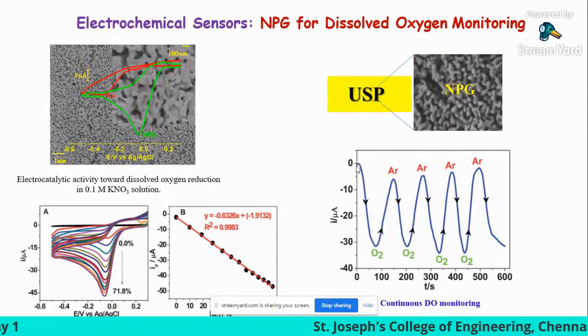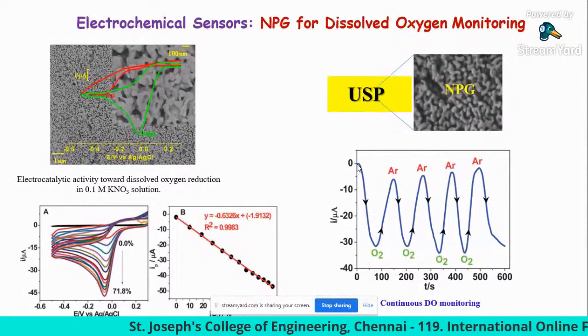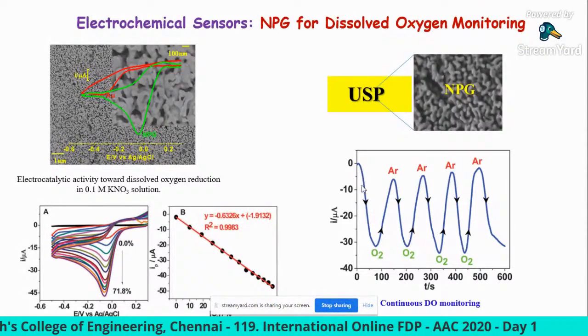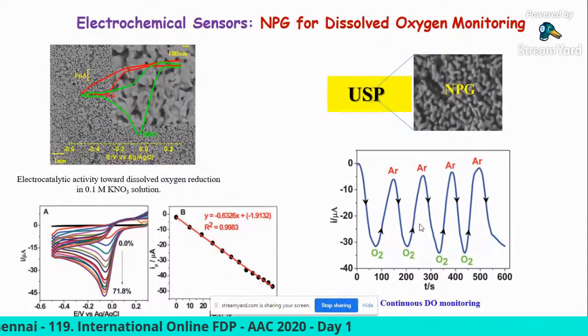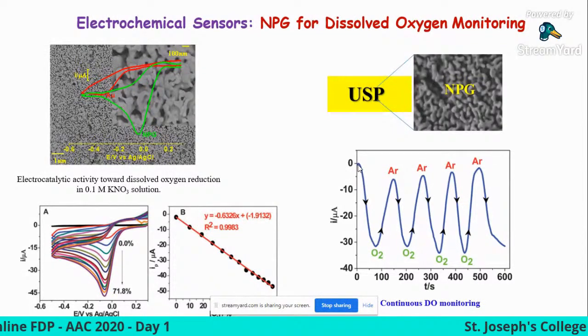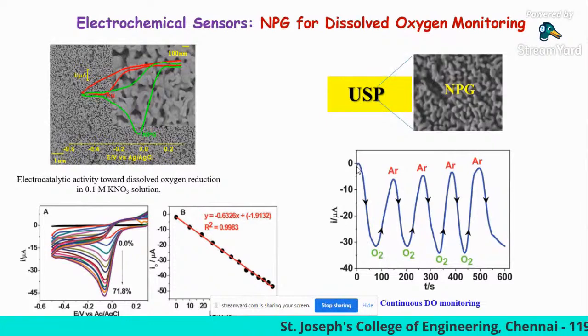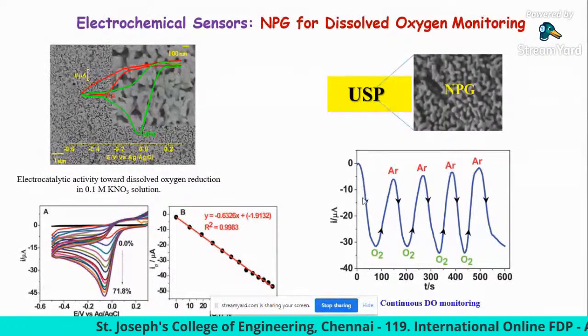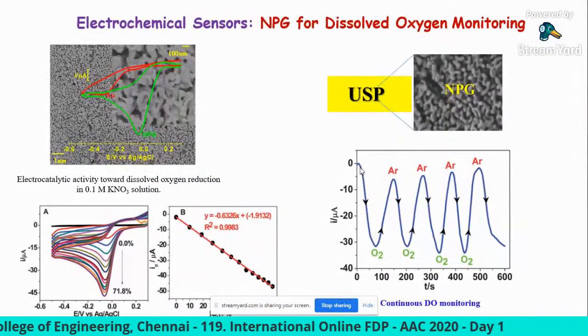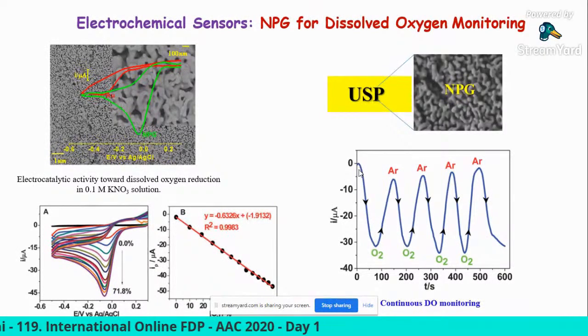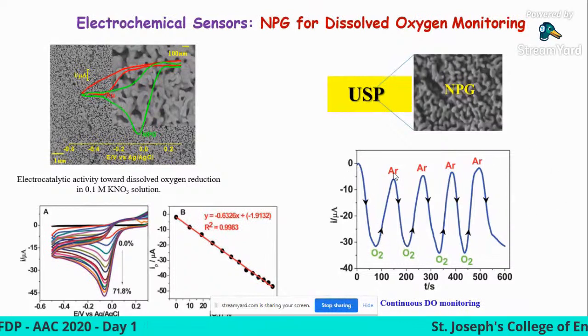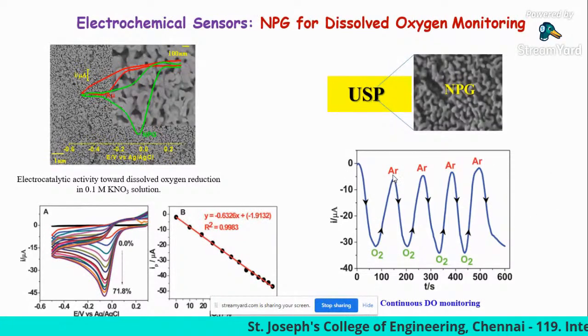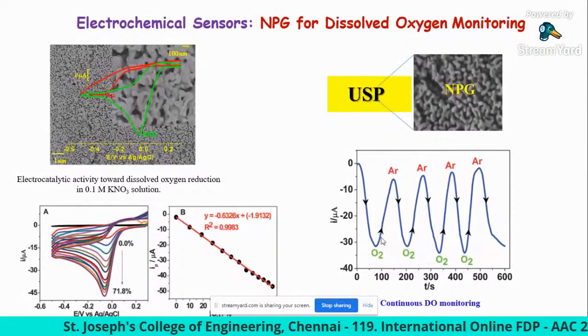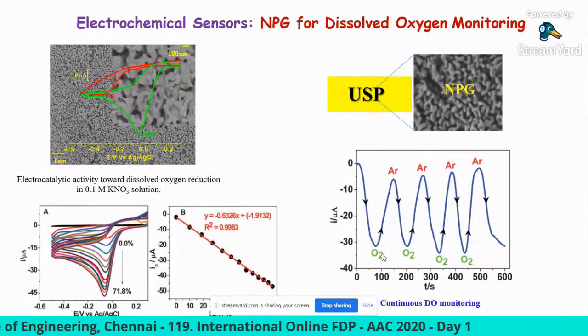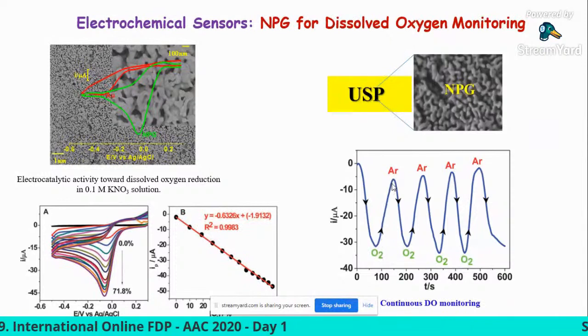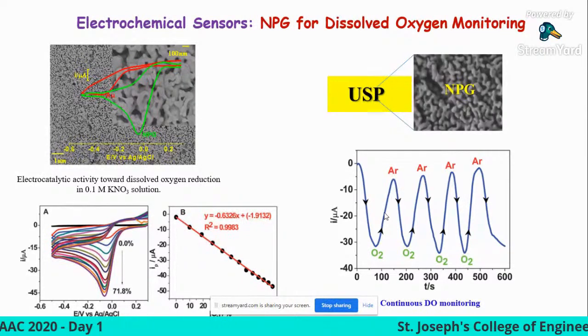So we monitor the current with respect to time at an applied potential of 0 volt. Here you can see initially the current signal is 0. When you pass the oxygen gas into the solution, this is recorded in potassium nitrate, so a neutral solution, you see the current signal increases, which means the oxygen concentration increases in the electrolytic solution. Then if you pass the argon gas, it removes the oxygen from the solution, which means when you pass the argon gas into the electrolytic solution, the current signal is decreasing, which means the oxygen concentration is decreased in the solution.